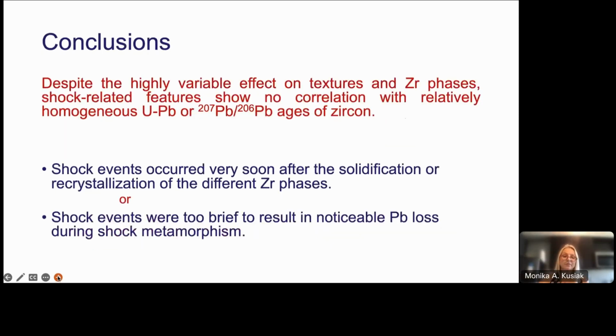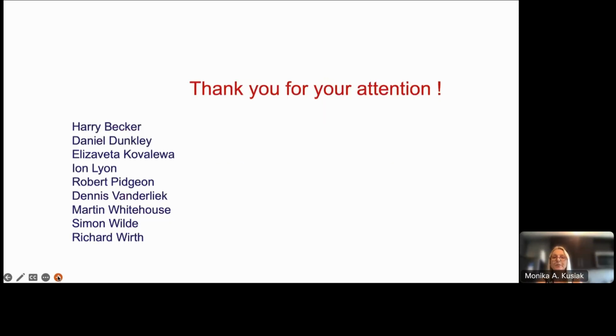glass. And just the conclusion: it was quite surprising to see so many textures in the zircon phases with such uniform 207Pb/206Pb ages and uranium ages, which was really very surprising for us because we didn't expect this. So the conclusion is that either shock events occurred very soon after the solidification or recrystallization of these different zirconium phases, or these shock events were too brief to result in noticeable lead loss during shock metamorphism. Thank you for your attention.